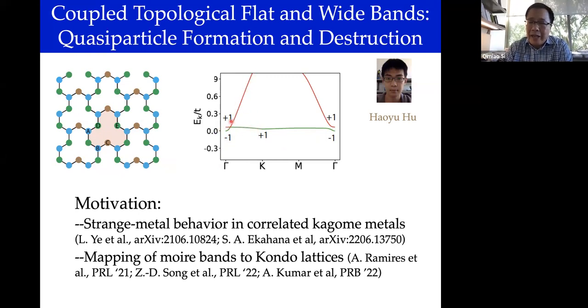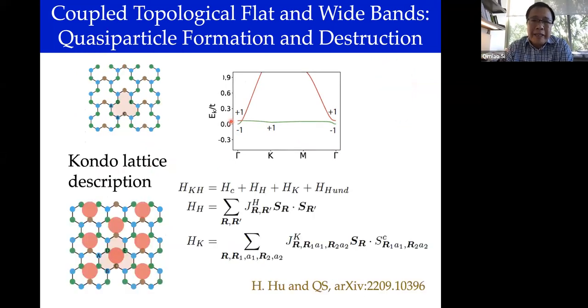And then there's also a wide band, which is just a toy model, just to make a point. So in spite of this topological non-trivial nature of the bands and the usual obstruction that it imposes on forming the real space description, for this case we were able to construct the Wannier orbitals, which primarily capture the flat band. It forms a triangular lattice sort of embedded in this lattice, and these are especially localized Wannier functions.